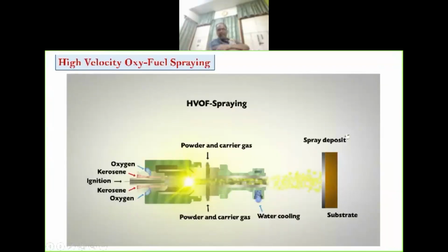Its cousin, big brother, HVOF. The process is very similar, but this time we put in either liquid fuel or gas fuel at a very high pressure, along with oxygen at a very high pressure, and set the mixture ablaze. It is allowed to remain constrained for a while in a long chamber so that pressure builds up, and when it exits through this narrow nozzle, it goes out at a high speed.